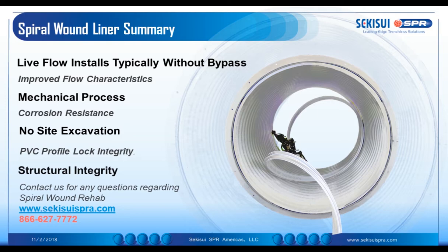I mentioned during the presentation that we have conducted testing of liners at small diameter in both laminar and turbulent flow conditions. Our testing achieved values ranging from 0.008 to 0.0094, and we employ 0.009 to be consistent with industry expectations for plastic pipes.